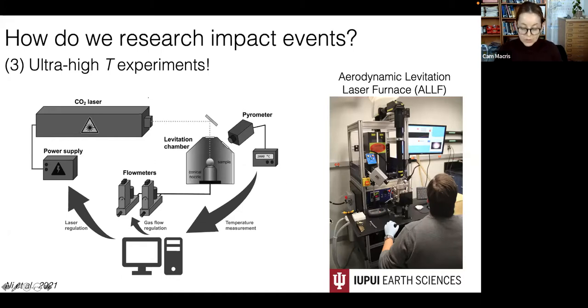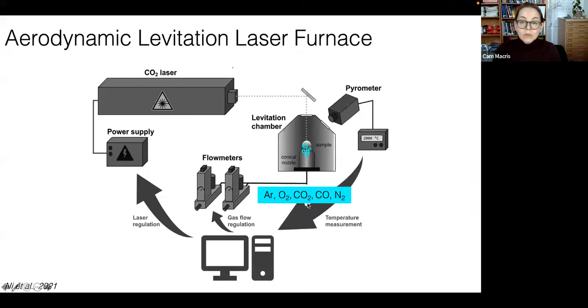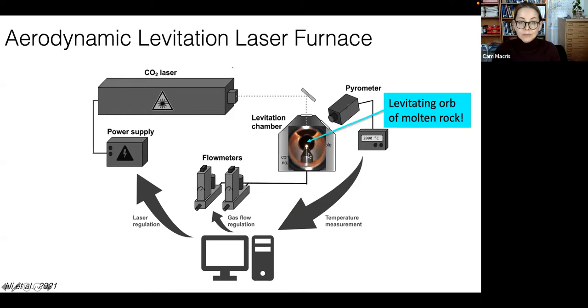The action is all happening behind this welder's glass in this chamber here. And here you can see a photo of what it looks like if you were to look inside, which you would not want to do. So this is the molten spherical sample, which is levitating on top of this nozzle. We can use a variety of gases for levitation, such as those listed here. And we can even mix them to create different environments for experiments. So the gas is what allows the sample to float above the nozzle while it's being heated. So what we end up with is a levitating orb of molten rock, which is pretty cool.